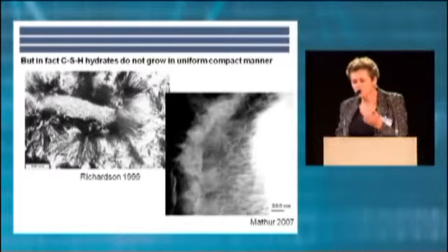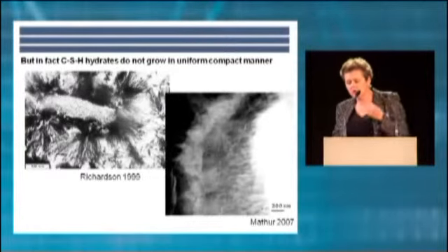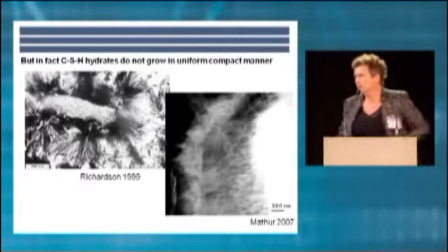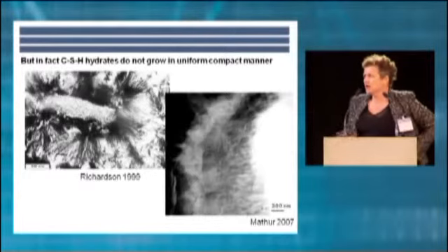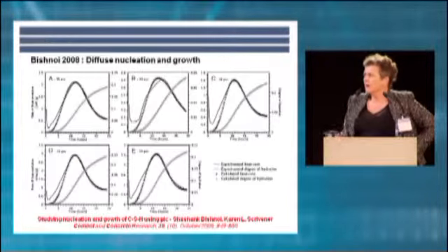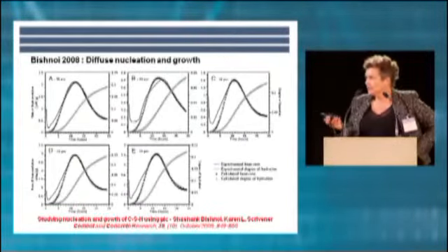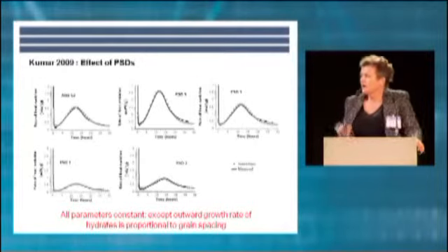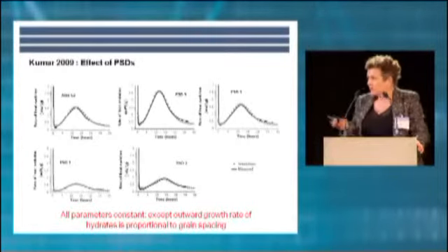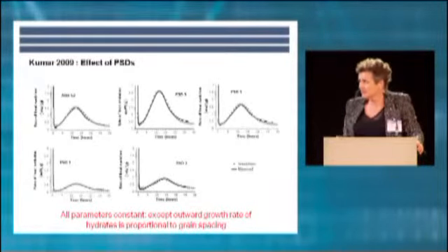So it's not a uniform growth; it's something that grows out very fast in a very diffuse manner and then subsequently densifies. And when we capture this kind of reaction mathematically, we can then get very nice fits across the range of particle sizes. So we can put all that together. Here you see the fitting across the range of particle sizes.